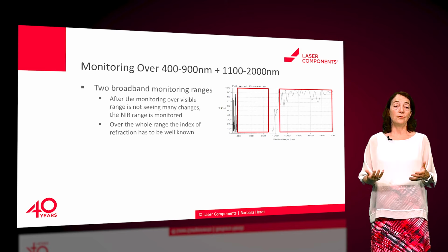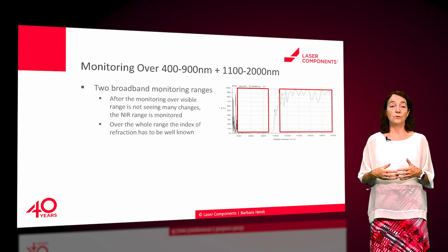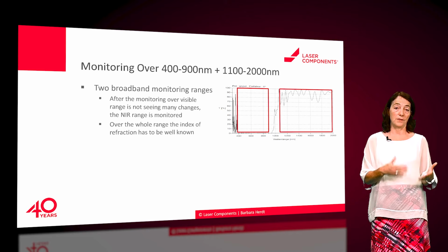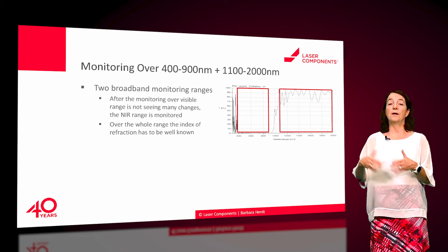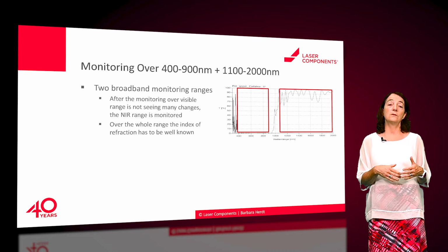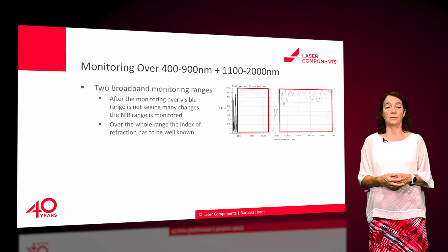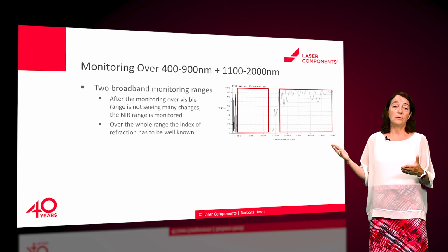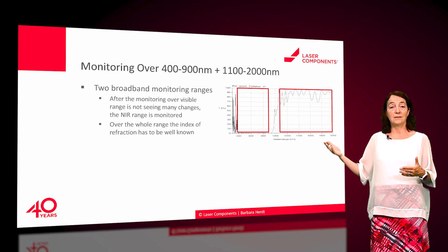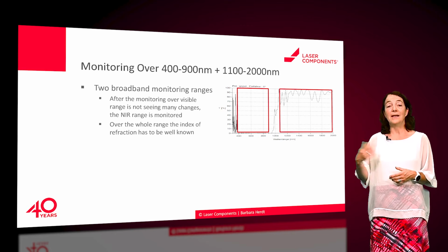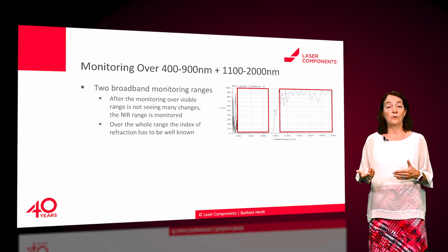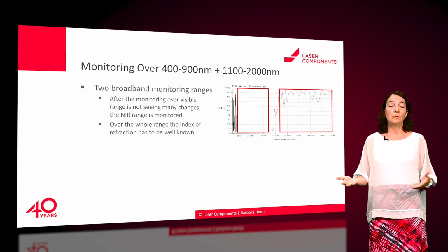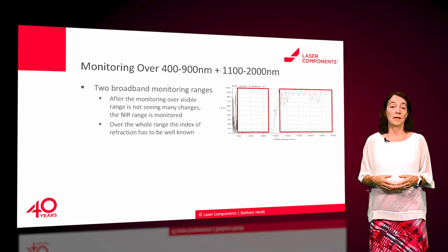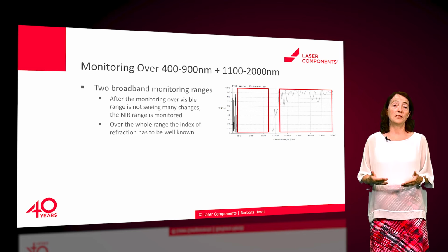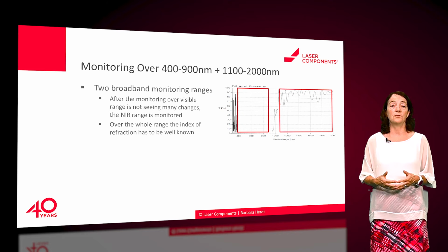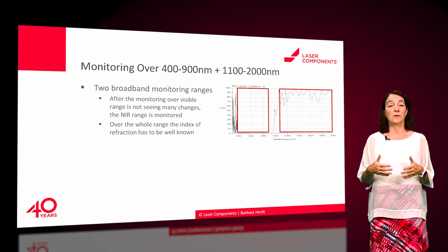Then we have now in our new large IBS chamber the possibility to use two broadband monitoring systems at two wavelength ranges. In our case, 400 to 900 nanometers and additionally 1100 to 2000 nanometer at the same coating run. The 400 to 900 will be used for the first layers till the accuracy is not any longer good enough. Then the second wavelength range will be used for monitoring, as there is still enough information available to reach a good spectral result. As I have said before, the index of refraction must be well known. This is chamber-specific information and something that is verified on a regular basis.